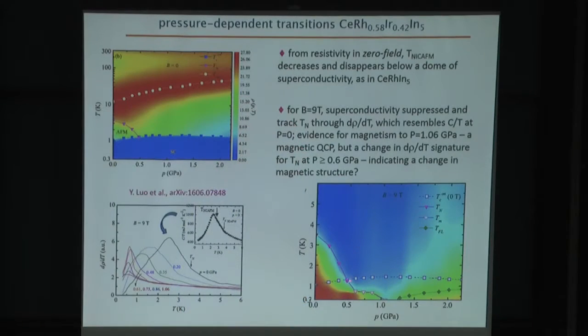And the results of these experiments are summarized in this, again, temperature-pressure phase diagram that's constructed for an applied field of 9 Tesla. And what we see is that the magnetic transition drops very rapidly. There's a clear change in character of the signature for the resistivity, but there's also a clear change in the pressure dependence of these features, and that's reflected in this shoulder here. So we see that any evidence for the magnetism disappears at a pressure of just a little over 1 GPa or so, and that there is a clear change in at least the pressure derivative, if not the nature of the magnetism, at a lower pressure.